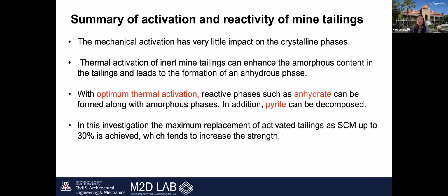So the key findings show that optimal thermal activation plays a crucial role in improving the reactivity of mine tailings, and that this happens by increasing the amorphous content and forming reactive anhydrous phases. And at the optimum activation temperature, anhydrite and other reactive phases are formed, while pyrite and other unwanted minerals are completely decomposed. And these changes lead to better performance of the material in cementitious systems.